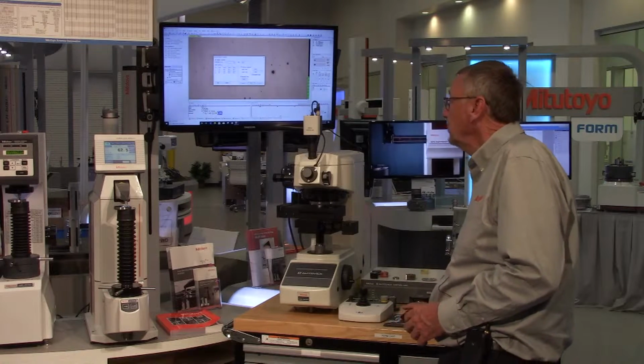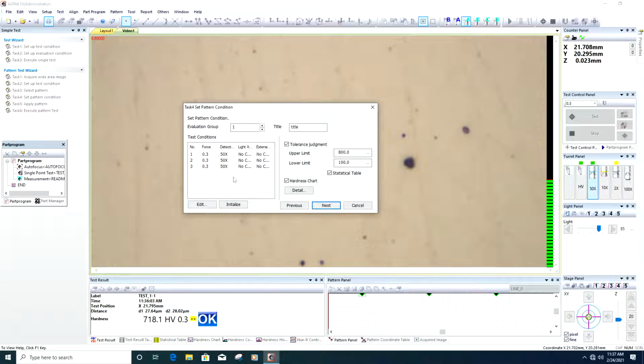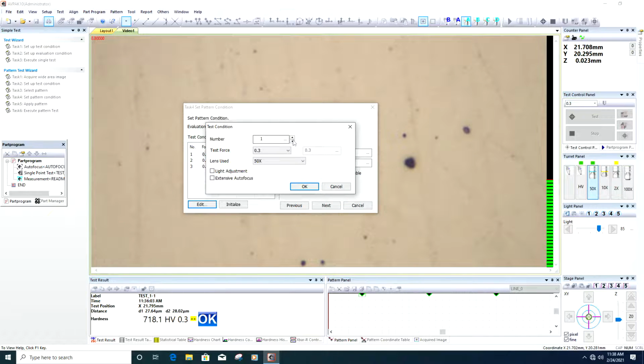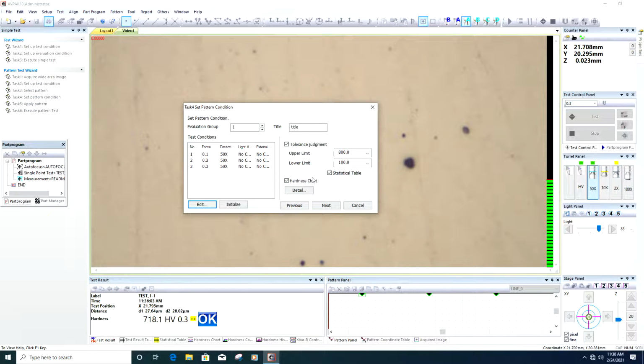Okay, those 3 points come back. This is a really powerful screen that you may or may not use. For example, when you start very, very close to the edge of a sample, ASTM ISO, I'll say you have to be 3 diameters of your indentation away from the edge. Okay, well, if you have a big indentation, that means you've got to be far away. Right. So what we could do here is just edit the first one and say, I only want to use 100 grams. And I still want to use my 50x objective and whatever, but I can change any of those parameters for any of the indentations.